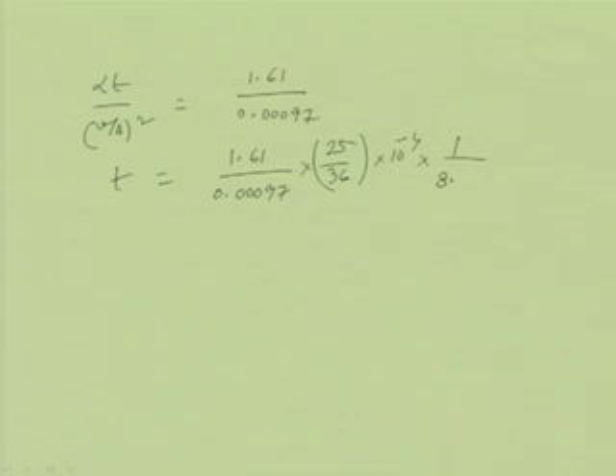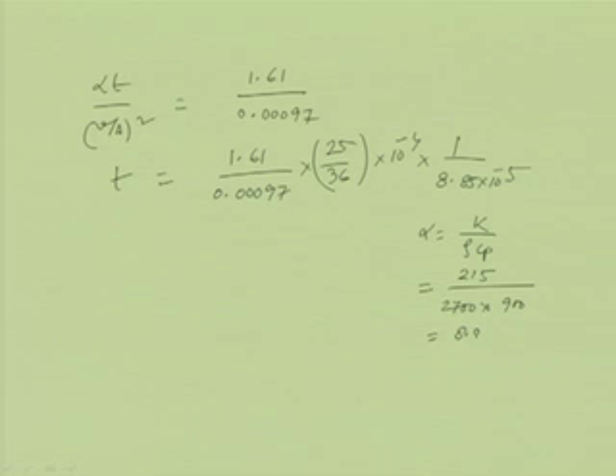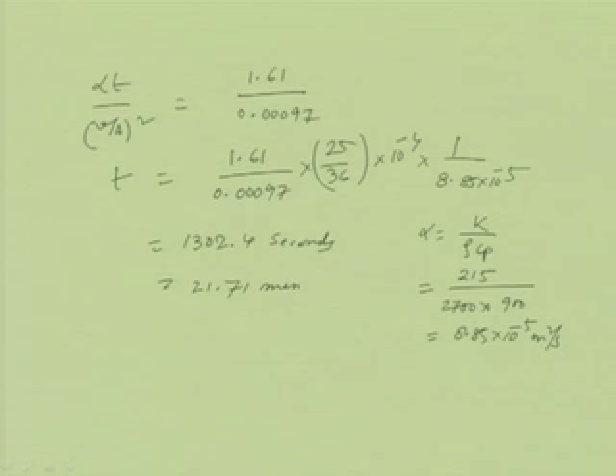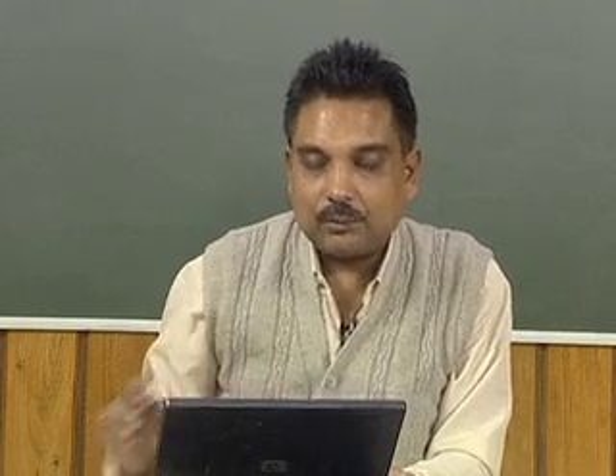Alpha is equal to 8.85 into 10 to the power minus 5. How do we calculate alpha? Alpha is equal to k by rho C p, and the values are given: k is 215, rho is 2700, C p is 900. This gives 8.85 into 10 to the power minus 5 meter square per second. If we put these values here, we get 1302.4 seconds, which is 21.71 minutes. That means the aluminum cube will come down to 40 degree centigrade at 21.71 minutes. So this is the problem.